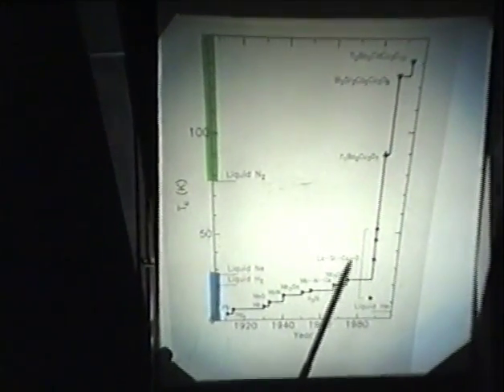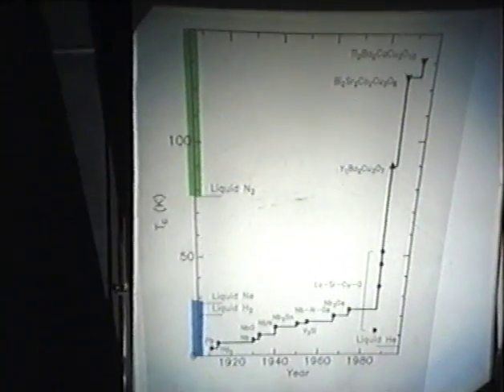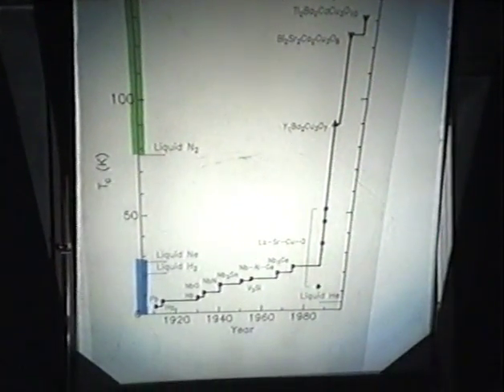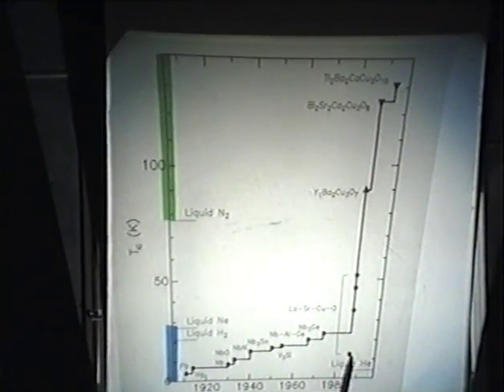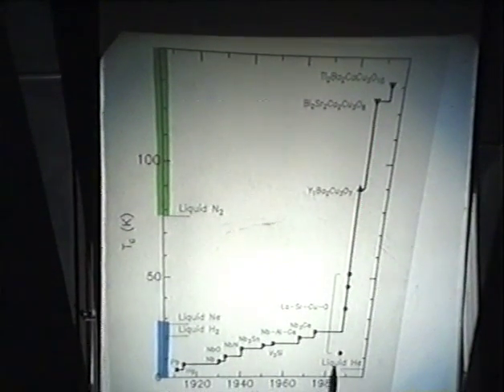So they got some copper oxide and tossed in a bit of lanthanum and strontium, and bingo, they hit the jackpot. Straight away they found quite a respectable critical temperature down here. You've got to keep in mind that this perovskite structure is actually a ceramic, it's not a metal. And it does conduct electricity okay a bit at room temperature, but of course it went superconducting, their first sample, which was a great surprise, really, considering that it's a ceramic.